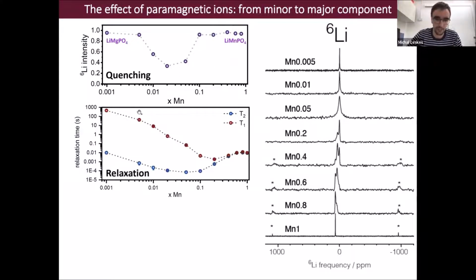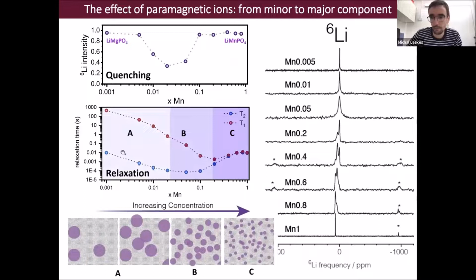And if we want to understand this figure, we can look at the relaxation behavior of these samples. So here in red are the T1 relaxation and in blue the T2 relaxation time for these same concentrations. Let me split this figure into three parts. In the first part, at this low concentration regime, the T1 and T2 relaxation times drop very dramatically. Note that here the y-axis is a logarithmic scale, but the ratio between T1 and T2 stays constant, meaning that the electron relaxation time stays constant.